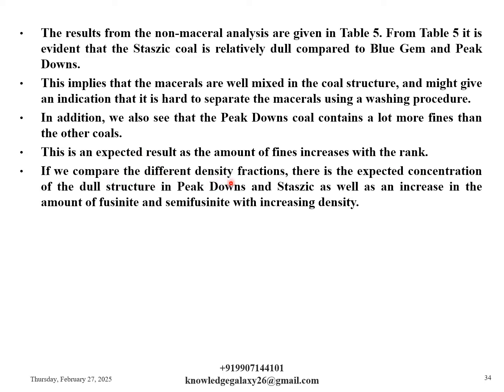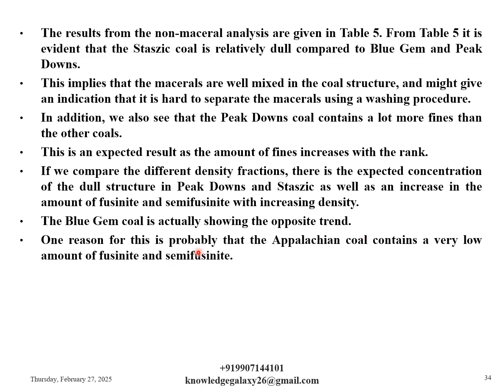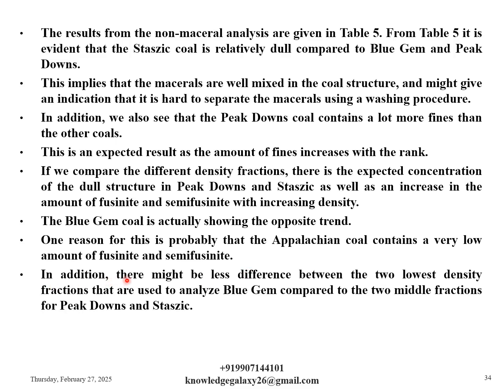If we compare the different density fractions, there is the expected concentration of the dull structure in peak downs and strategic, as well as an increase in the amount of fusinite and semi-fusinite with increasing density. The blue gem coal is actually showing the opposite trend. One reason for this is probably that the Appalachian coal contains a very low amount of fusinite and semi-fusinite. In addition, there might be less difference between the two lowest density fractions that are used to analyze blue gem compared to the two middle fractions for peak downs and strategic.